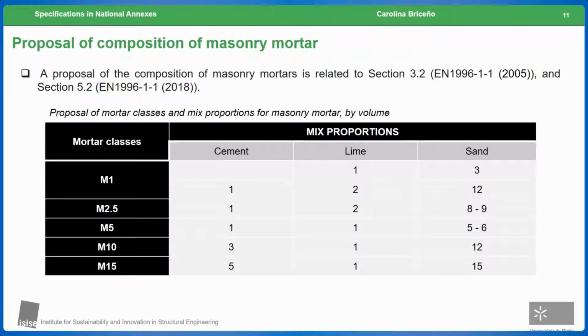Considering the previous information, it was possible to propose the composition of masonry mortar, obtaining the table that is shown in this slide. In order to build this mortar mix proportion, we consider three particular points. The first one is that we assess the proposals without taking into account the distinction between the type of lime that is used. The second point is that we consider only those proposals whose variations were less than ±6% among them. And finally, with the options that are available after the two previous points, we consider the average of these components in order to have the values shown in this table.